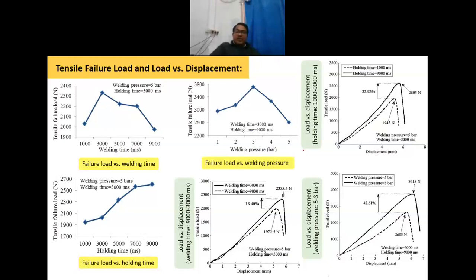So again, this is with respect to different parameters, how they affect the joint strength. As I have mentioned, welding time should not be very high, it should not be very low. At very high and very low welding times, it is not giving me an adequate amount of strength. At a moderate level of welding time, I am getting the maximum failure load. Similarly, welding pressure should not be very low or very high. At a moderate level, it gives me the maximum failure load. But for holding time, higher is the better. At a higher value of holding time, it gives me the maximum tensile failure load. And these are the load versus displacement graphs, a comparison of the different parameters.